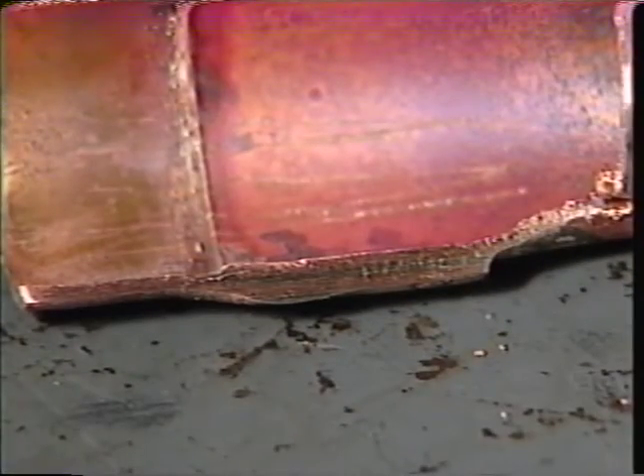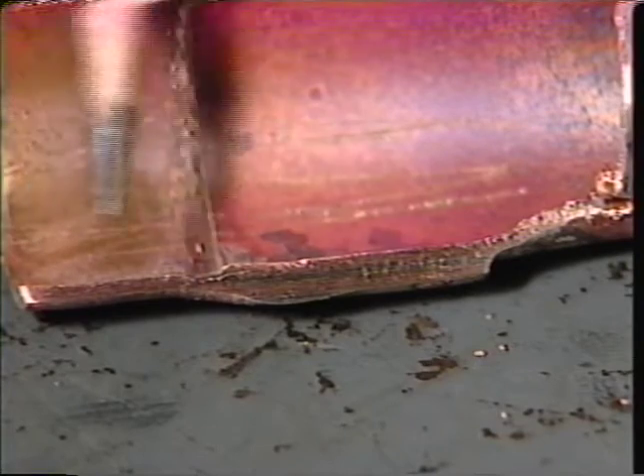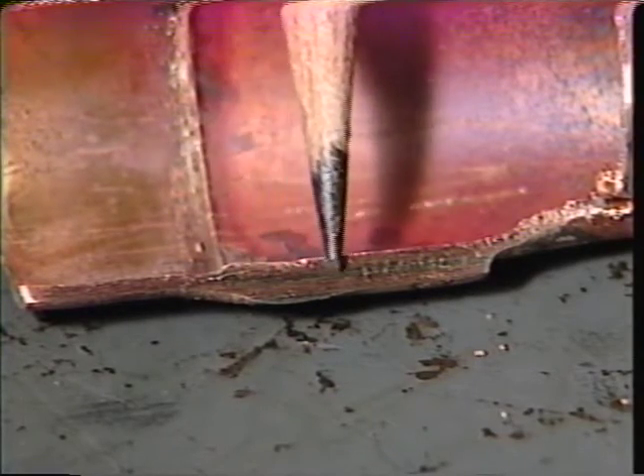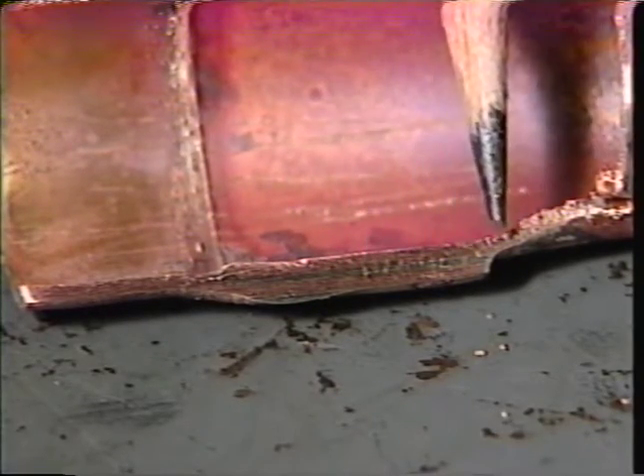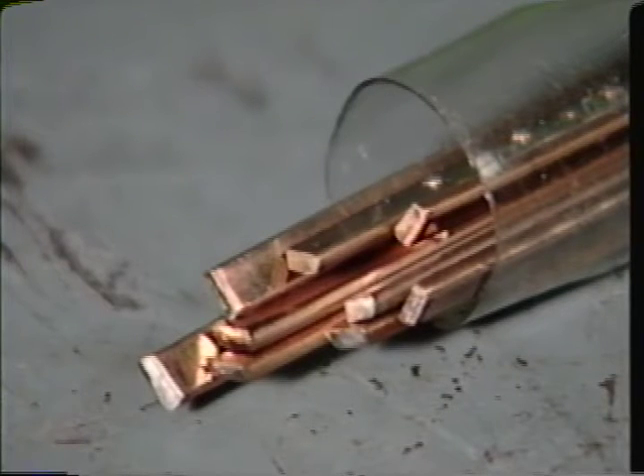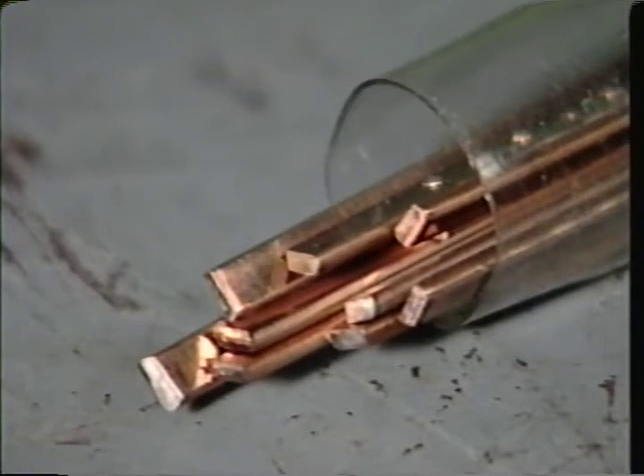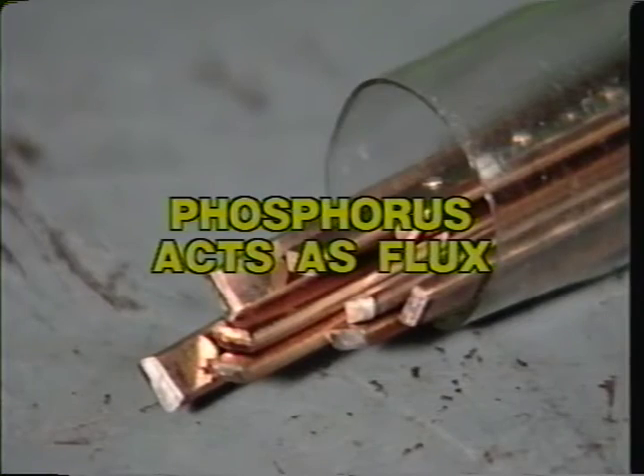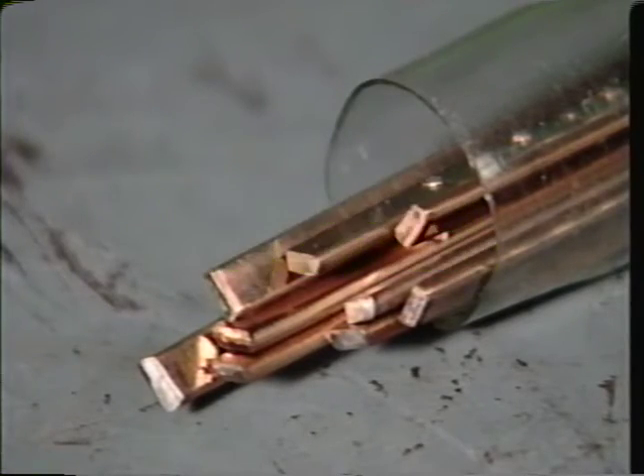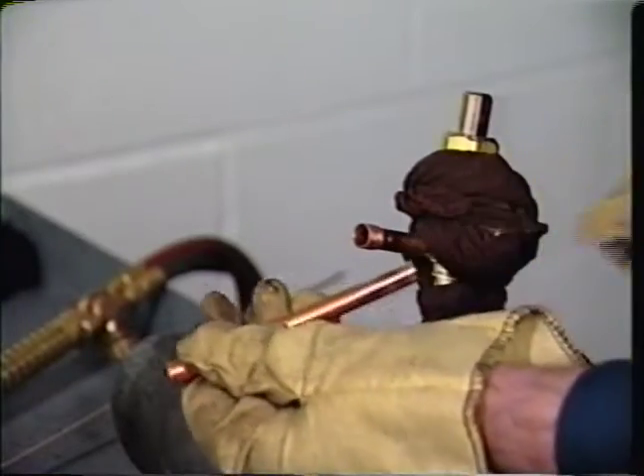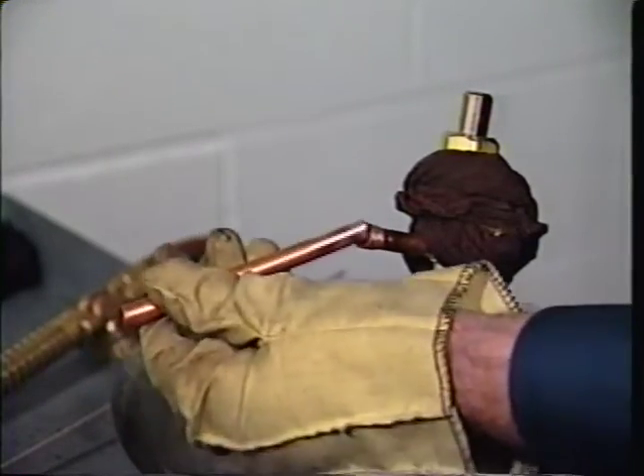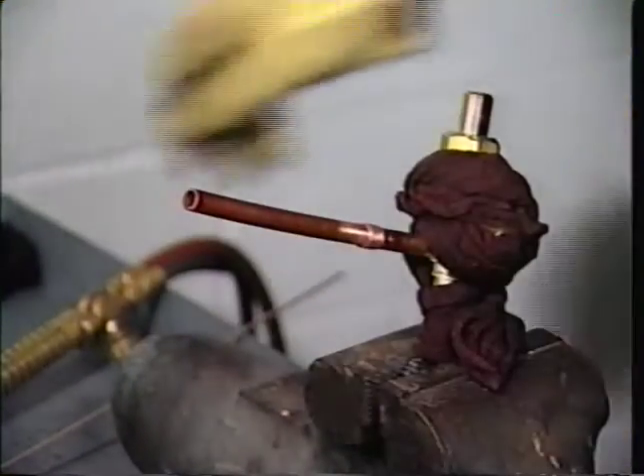Here, we've sectioned a brazed joint. Notice how capillary action has pulled the filler alloy deep into the joint. Many service technicians prefer to use a fluxless copper-phosphorus brazing alloy when making copper-to-copper connections. This brazing alloy contains phosphorus that performs the same function as flux. The same preparation procedure is followed as previously described, except flux is not used.